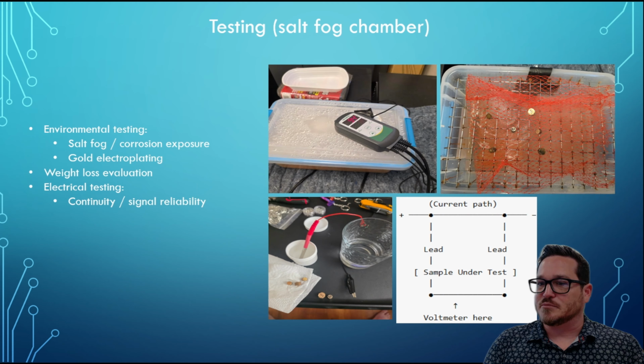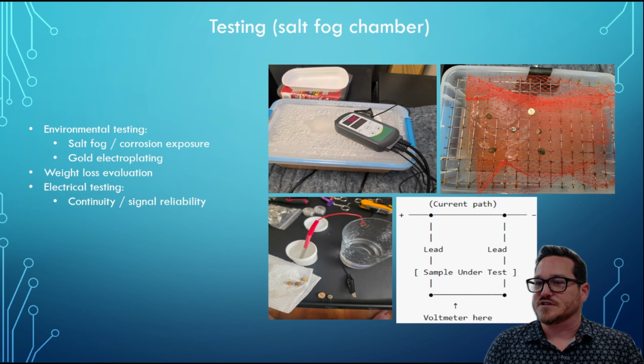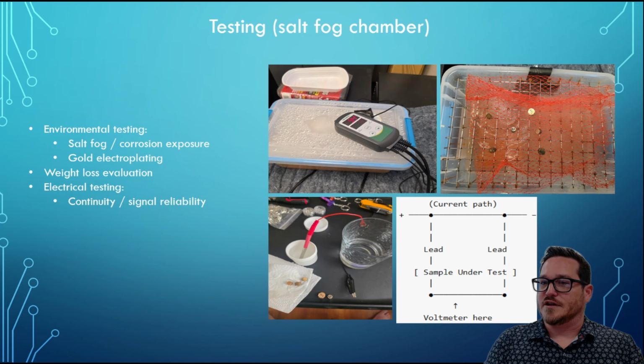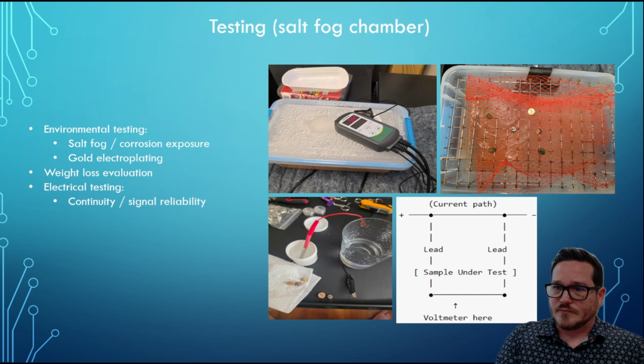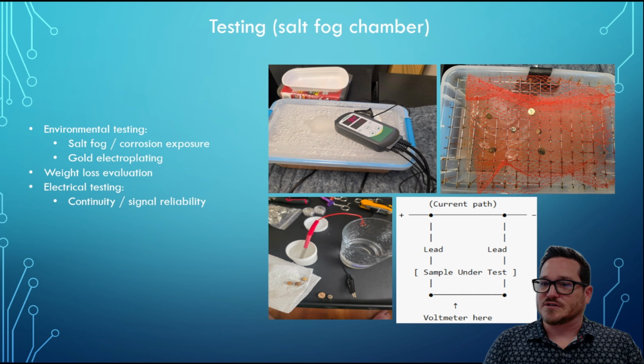I set the desired temperature to 100 degrees Fahrenheit, and the controller powers on the heating pads until the chamber reaches that temperature. While this is happening, the fogger is creating a saltwater fog that fills the heated chamber. I left the test samples in the chamber for 96 hours. Also, for the metal samples, I took 2 small sections of each of the 3 metal rods.